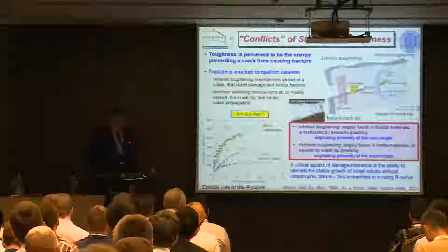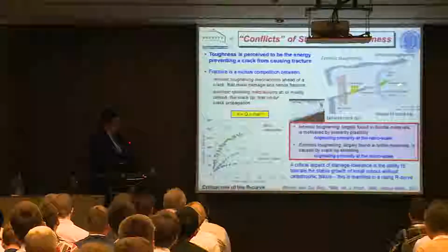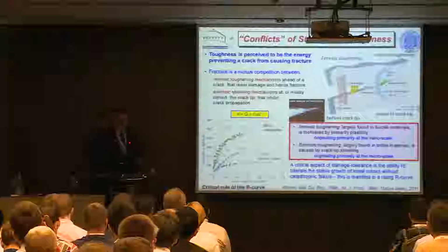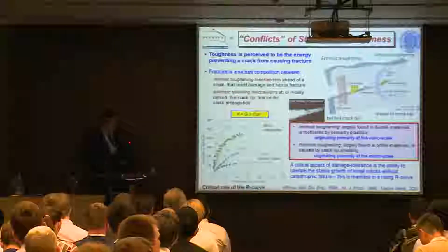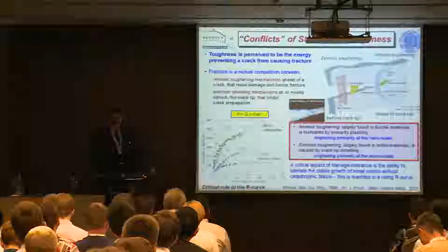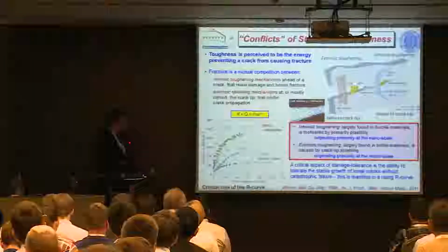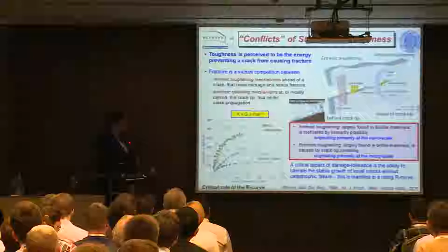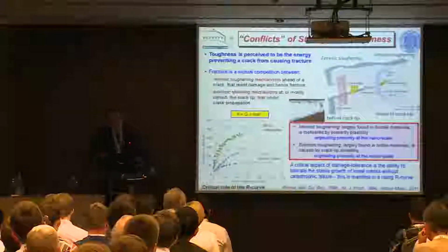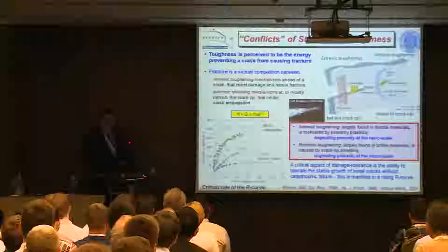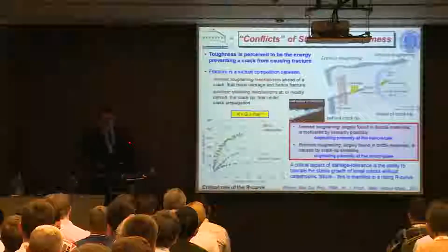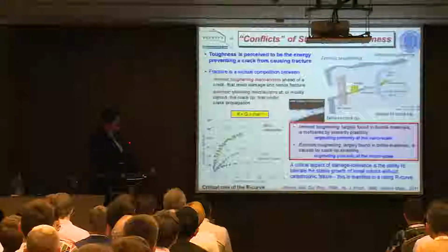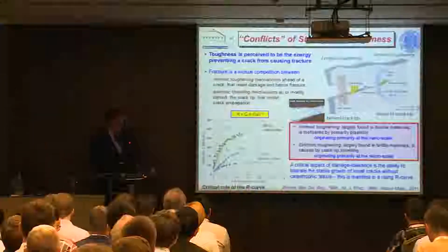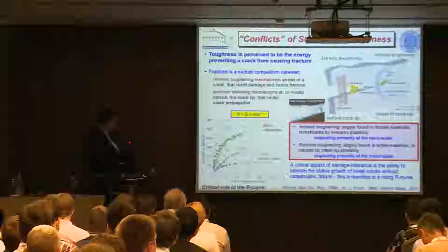Now there's an interesting contrast here. These plasticity or intrinsic mechanisms originate typically around the nanoscale, but these mechanisms can operate at any scale. In fact, in bone, we'll see that these mechanisms operate on the scale of hundreds of microns. These are a property of the material, and these depend on the geometry of the crack and so forth. These mechanisms have simply no meaning for initiation. You have to have a crack to have an extrinsic toughening mechanism, so these only operate for crack growth. And what's interesting about this is that these mechanisms, although plasticity is the same thing, generate the so-called R curve.